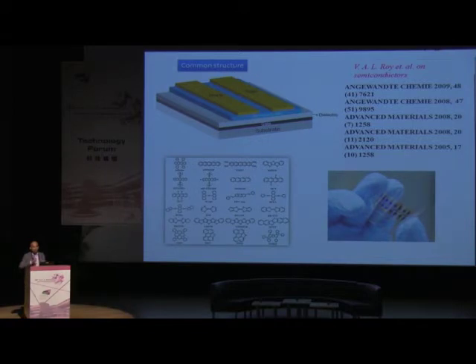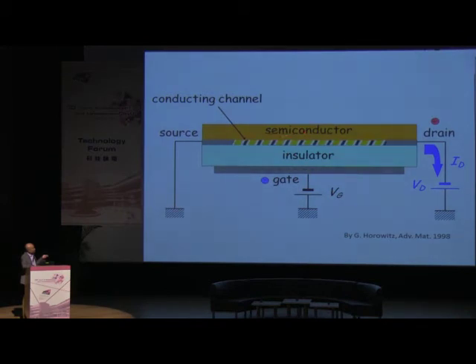These traps always behave like an obstacle for the charge when it is transported, as we saw in the previous slide. When the charge flows on the semiconductor, in the first two or three to four monolayers, these traps behave like an obstacle for them to flow. Basically, they trap these charges at the oxide interface. Now, this is one of the main reasons why these devices do not have a high mobility. So can we use this for other purposes? That's what we did. We can use these traps to store the charges. Whenever you want to release the charges, you apply a negative bias and release them. So it's basically like program and erase. This is where the memory device is born.